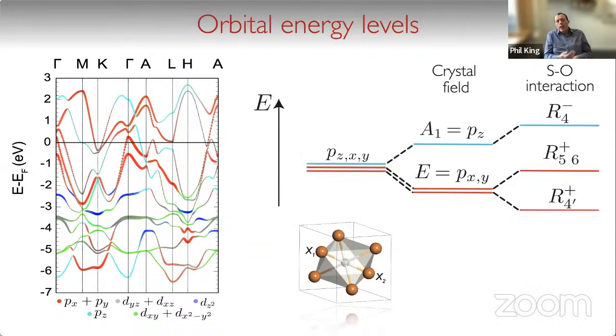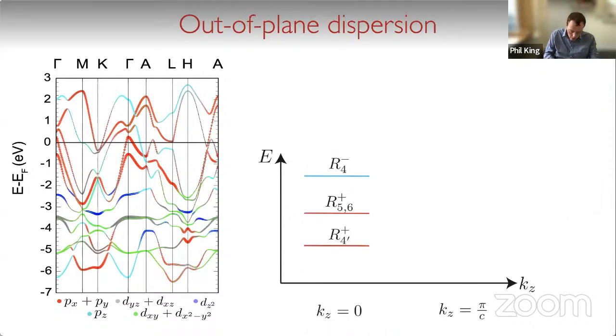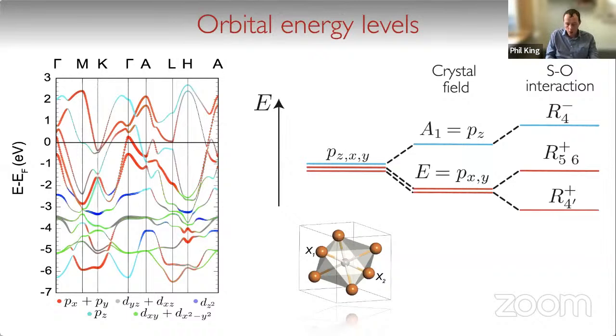Okay, so with this thought that the p states here are really the thing that's dominating the electronic structure, I'd like to walk through a really very simplified picture of how we can think about the electronic structure derived from these different p orbitals. And so we of course start with our three p orbitals, our px, py, pz orbitals. And in this system here, these p orbitals sit in a trigonal crystal field. And so this trigonal crystal field will split off the energy of our pz derived state above that of our px and py derived states.